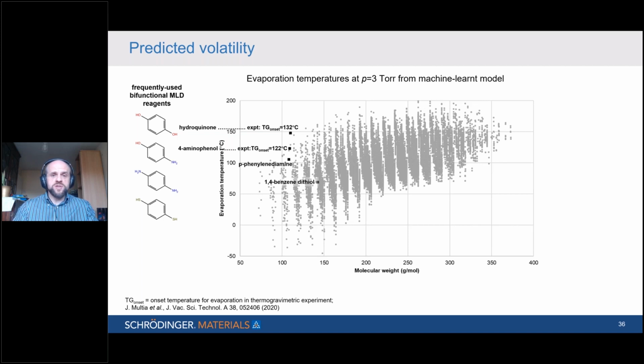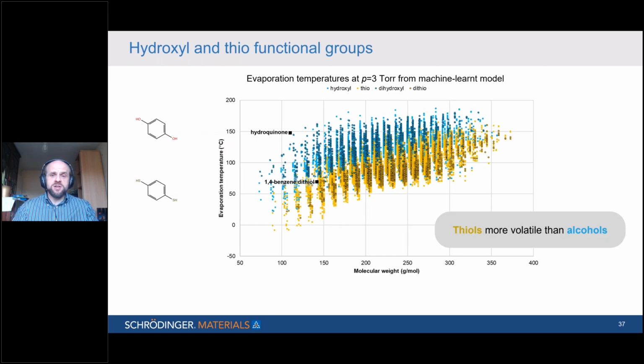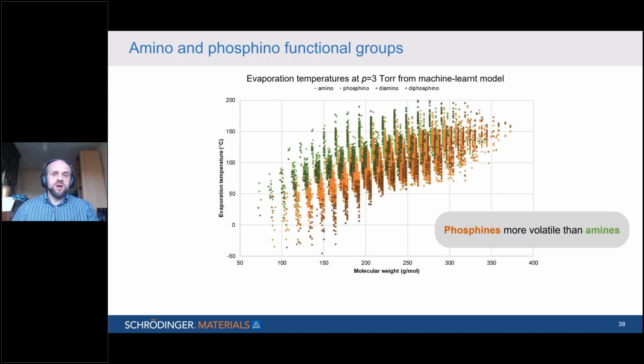So let's look at some of the other trends that we can see in the data. This is comparing thiols in yellow against alcohols in blue. And you can see that the thiols are universally more volatile. We also show here the dithiols and the dihydroxyls. Those are shown with the black circles. In a similar way, phosphines, shown here in orange, are more volatile than the amines, shown in green. And there seems to be more of a spread here across a wider range of evaporation temperatures.